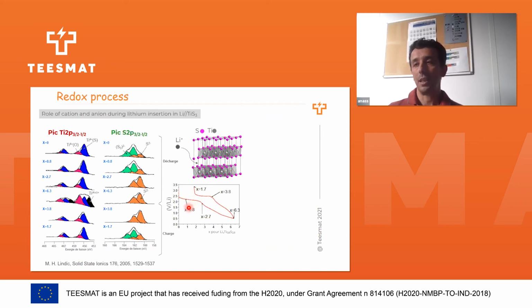When we start insertion, after 0.8 lithium inserted, we see an increase of the S2- contribution, but the titanium does not move. There is no change for the titanium peak. At 2.7 volt, lithium inserted, we can see that the second sulfide group disappeared and only the sulfur appeared. That means we have preferential reduction of sulfur. Up to now, the titanium does not move. At the end of discharge, the whole sulfur was reduced, but in the meantime, titanium was reduced.